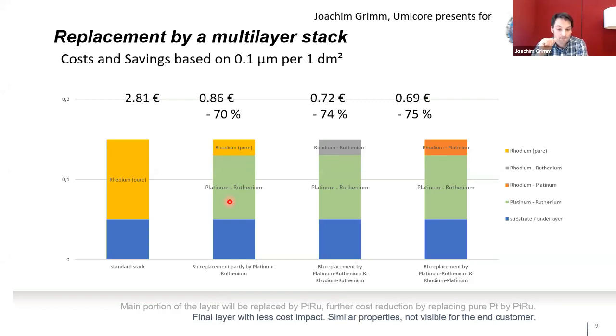The advantage is, compared to the pure platinum, the platinum-ruthenium alloys are higher or better in abrasive resistance, even though they are a little bit more dark than the pure rhodium. Nobody can see that under the layer of rhodium, and even if the first layer of rhodium would be wiped or scratched away, it is not visible; if there's a scratch, a little bit darker, still white color appears. Nobody can really see that or realize that there's a platinum alloy underneath the pure rhodium. Corrosion resistance is the same high level, and the quality of the same item is still high level platinum precious metal plating. And the saving step is here already at 70%.